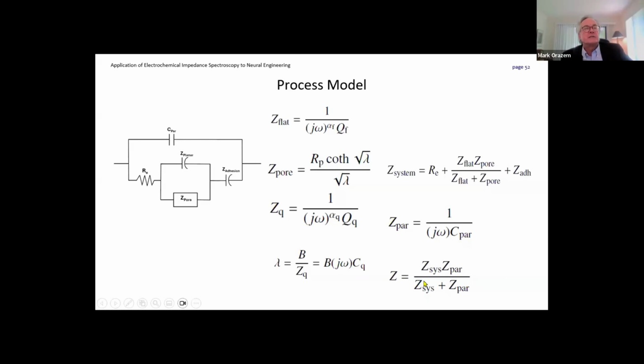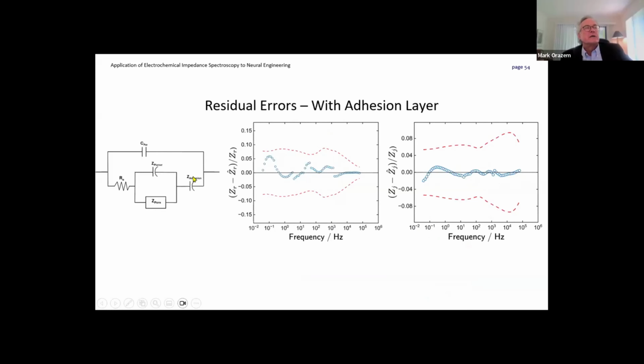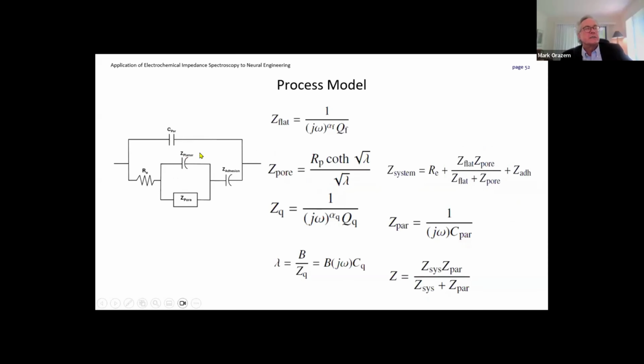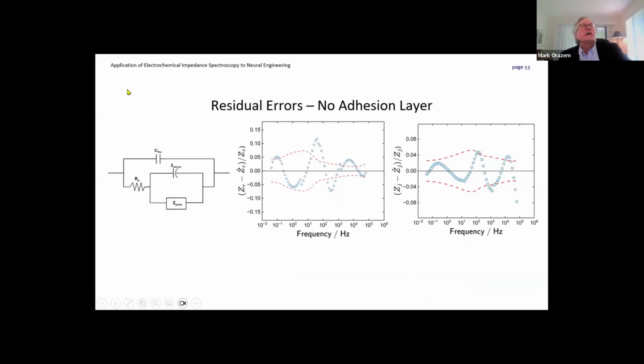And then the overall impedance is going to be the parallel combination of all of this. Let me go back up. So if I look at the residual errors with no adhesion layer, we're seeing residual errors that are really quite large. Again, this 0.15 would look like 15% up here.